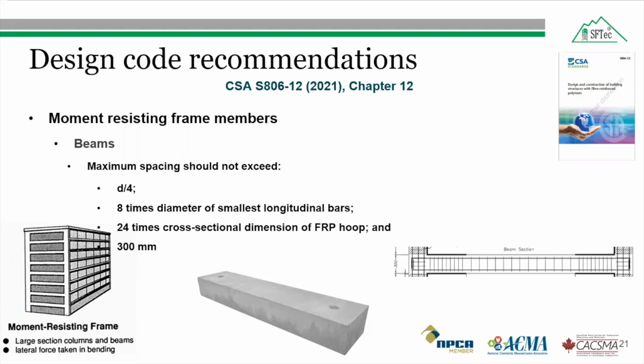of a supporting member. The maximum spacing of the hoop should be the minimum of 1/4 of effective depth, 8 times the diameter of the smallest longitudinal bar, 24 times the cross-sectional dimension of the fiber reinforced polymer hoop, and 300 millimeter. And further, the shear resistance of the beam should comply with chapter 8 of the CSA S806. As you can see in this figure, generally the hinge will form at the support end. So here you can see there is a special detailing provided with the FRP hoop.